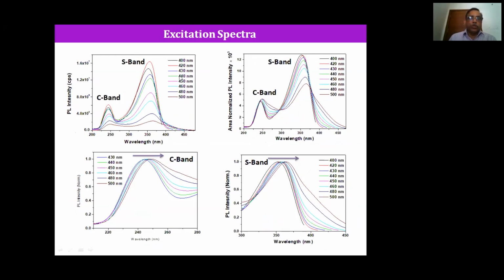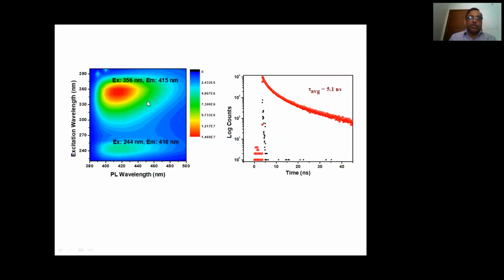We also looked at the excitation to see the different components present in the solution. We found that the core, the C band, and S bands were visible, and we made use of the 2D contour to find the multiple components present - giving 2 components in this solution.